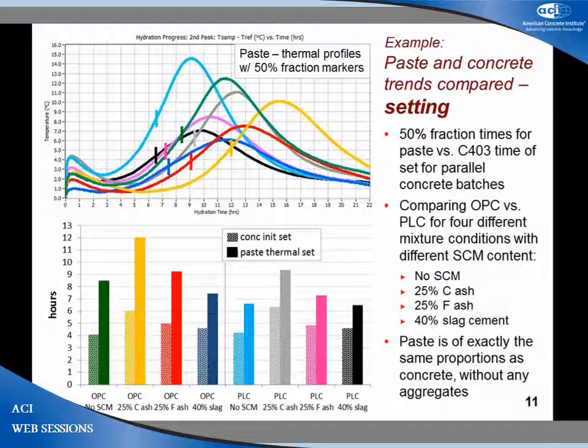In this case, the first bar, the shorter one, is the initial setting time, the C403 initial set by concrete penetrometer, and the solid bars are the 50% thermal fraction setting indication for the parallel paste mixtures in the laboratory. Again, you see all the same trends. If you wanted to calibrate that information for the initial setting times, you could use a fraction much lower than 50% and probably do a pretty decent job of predicting that concrete setting time.